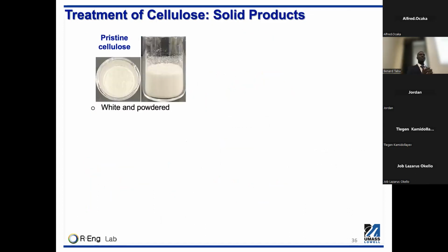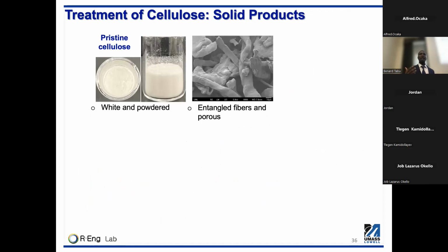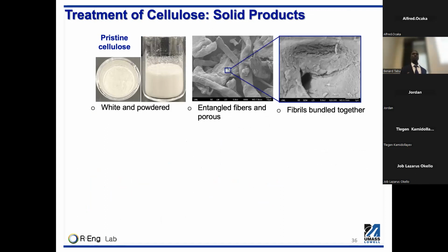We carried out a characterization of the solid samples. This is the optical imaging, using our camera. This is the cellulose. It's white and powdery, very sticky. But when you look at it under the field emission microscope at low resolution, we see that it consists of a network of crisscrossing fibers with a lot of empty space, and this empty space depicts high porosity. When we increase the magnification, we see that these fibers consist of fibrils which are bundled together, and it is difficult for us to distinguish them.